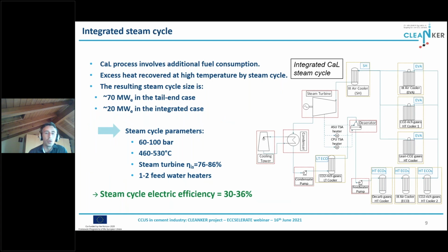One feature of all the calcium looping processes is that their application involves additional fuel consumption. But the advantage of this capture process is that the heat can be recovered at high temperature, because the carbonation happens at 650 degrees Celsius. So we can exploit the high operating temperature of both reactors for producing valuable steam and electricity.